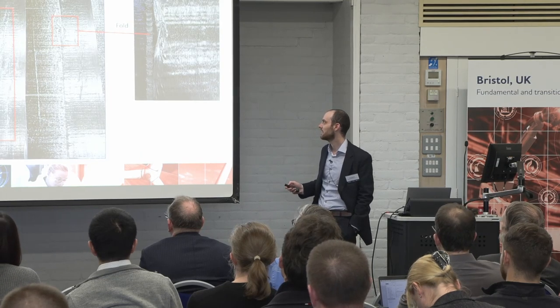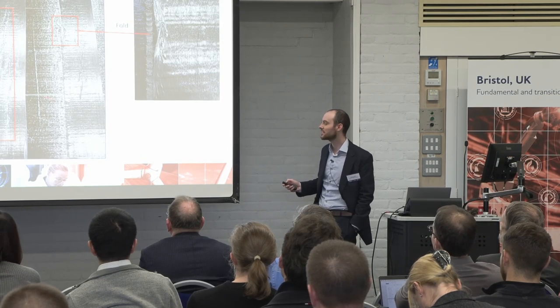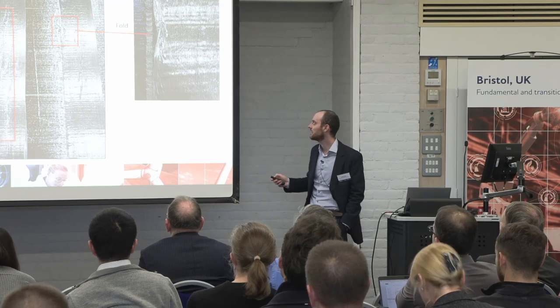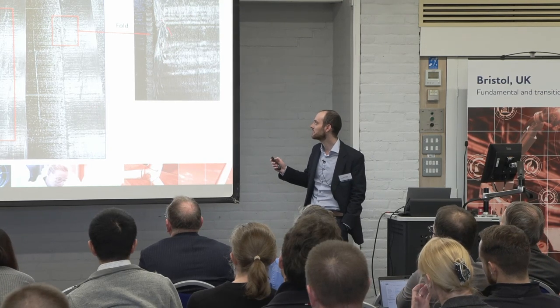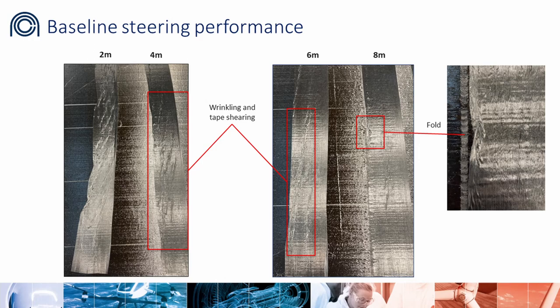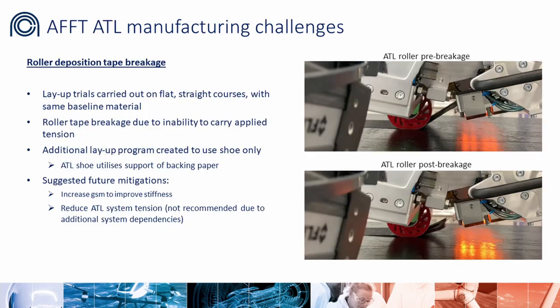This material is quite hard to take photographs of, so here's a bit of a close-up. You can see even at 8 meters you're getting a bit of folding. Carbon fiber is quite stiff. It really doesn't like shearing when you've got it in a wide tape format. But what we're looking for is, can we do this with a recycled material, particularly because of the short fibers?